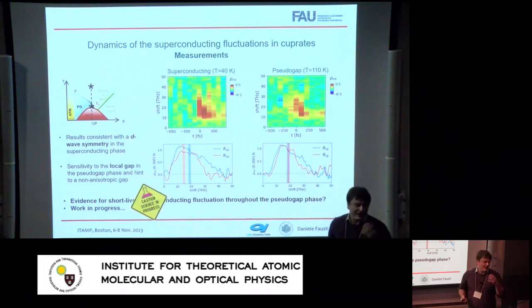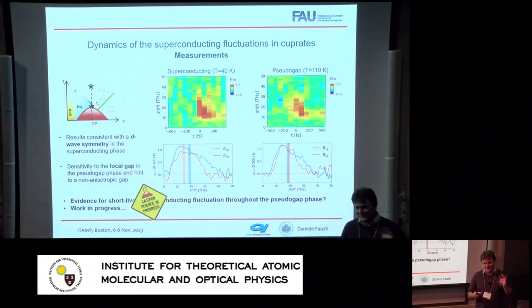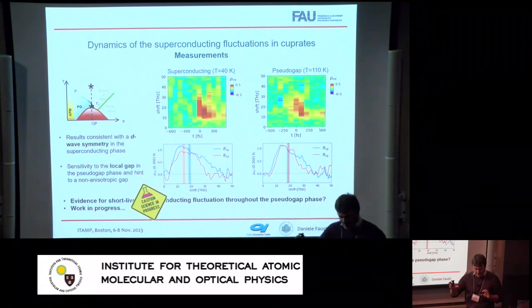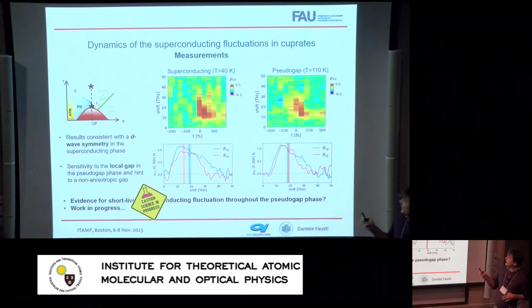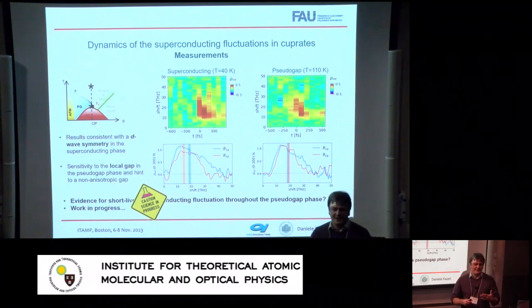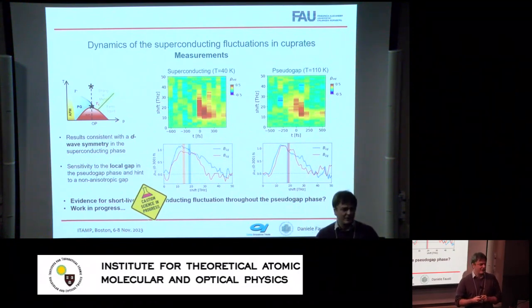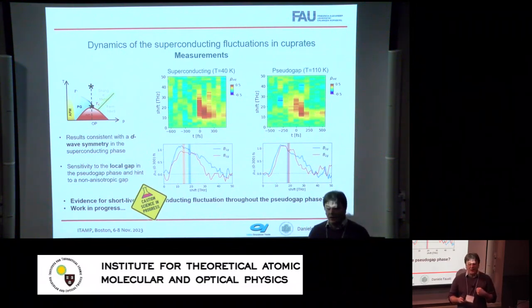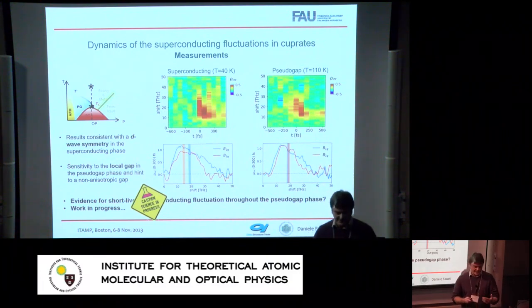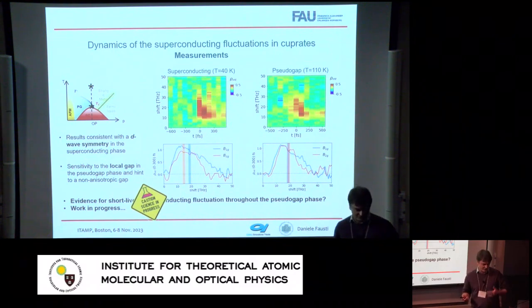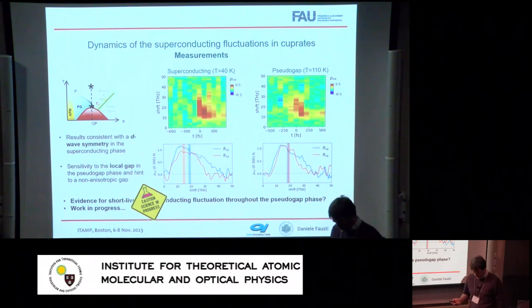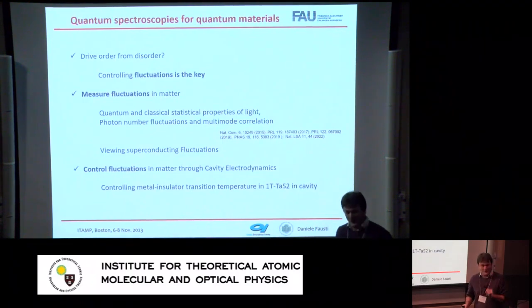Okay. What would be very interesting, we're trying to work on two sides. On one side, we're trying to consolidate this data, and on the other side, we're trying to look at how we should reason about it. But a very compelling reasoning direction is that the scattering feature I see above the critical temperature may be related to the fact that with this technique, I take snapshots of the interaction of my lasers, because the interaction time of my laser with the superconducting states is very, very short. So essentially, we're trying to reason whether this could be interpreted as yet another evidence of the presence of superconducting fluctuations above the critical temperature. But it's work in progress, so we just want to use it as an argument for where we will go at the end.